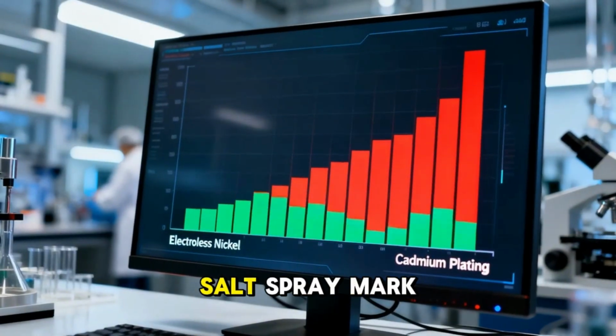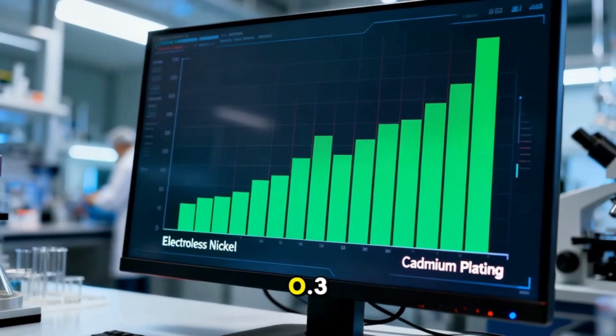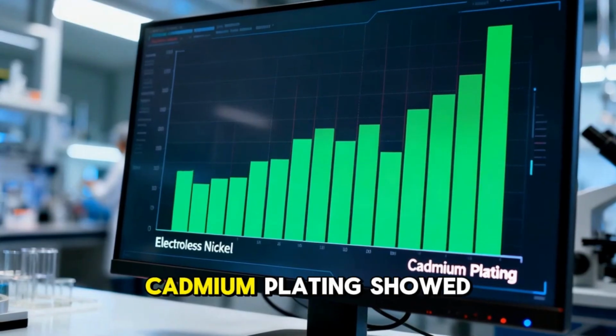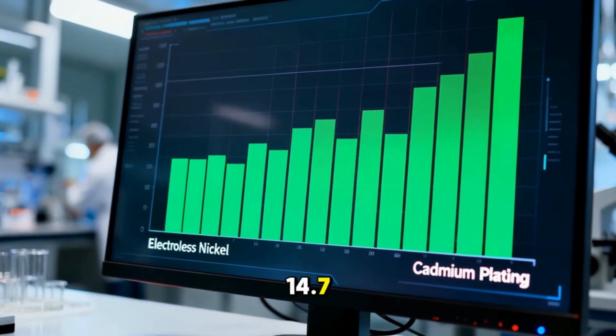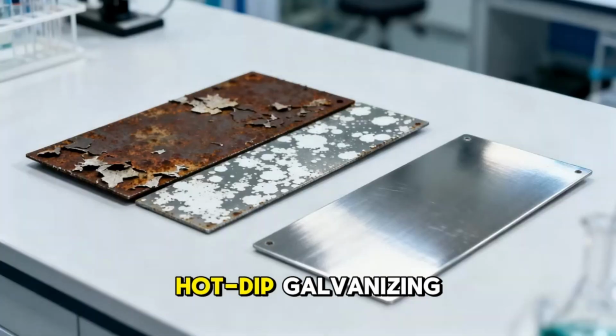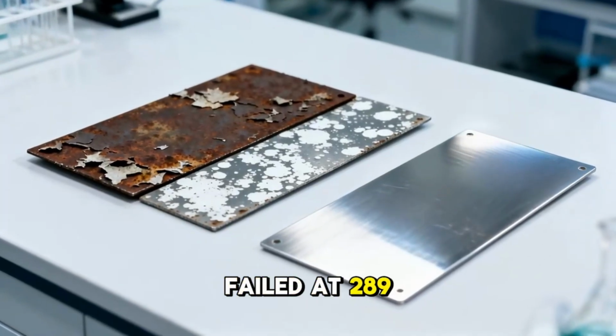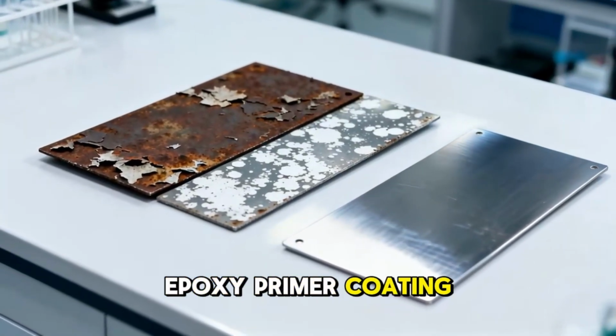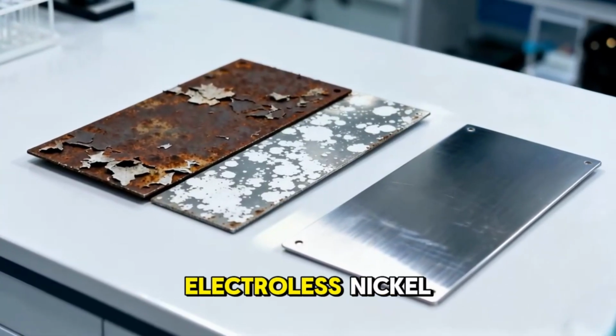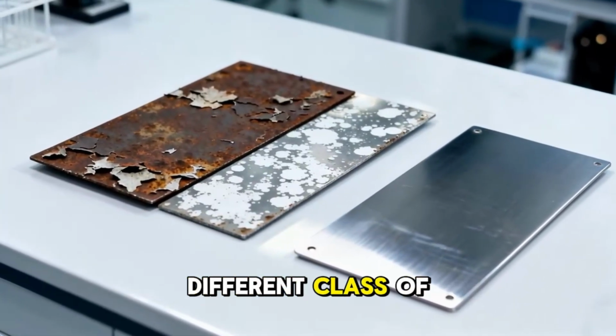At the 500-hour salt spray mark, Electroless nickel showed 0.3% degradation. Cadmium plating showed 14.7% degradation at the same interval. Hot dip galvanizing failed at 289 hours. Epoxy primer coating failed at 201 hours. Electroless nickel represented a categorically different class of protection.